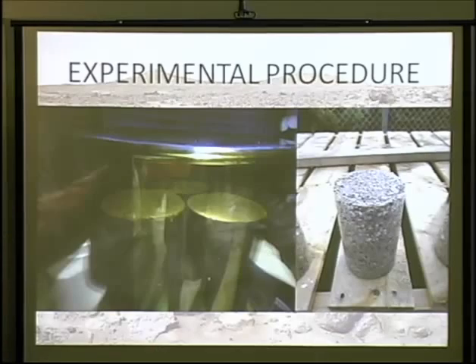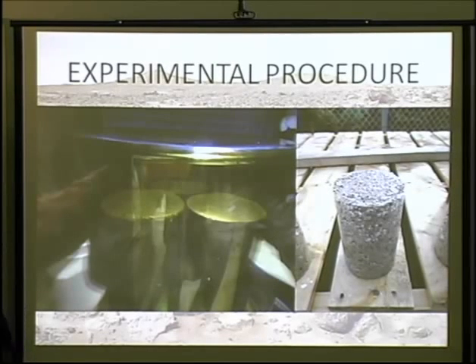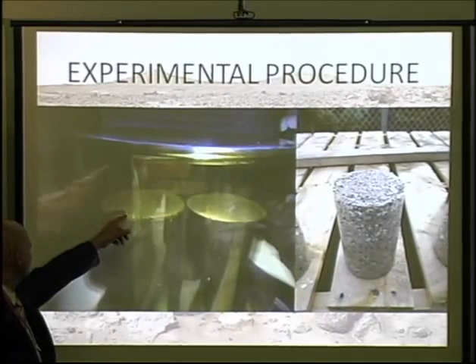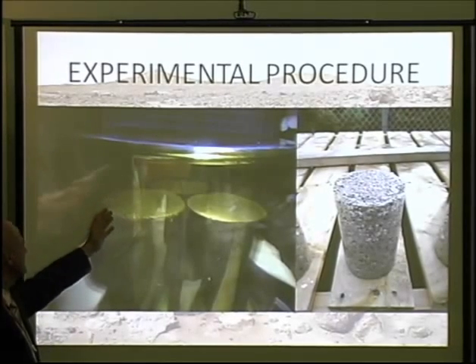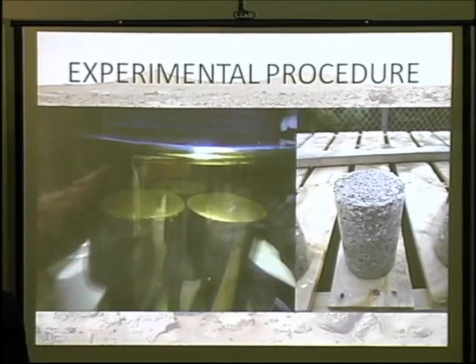So here are my samples in the vacuum chamber at 6 millibars. One problem I had was with dissolved gases that were in the brine and the mixed cement. Since I wasn't able to vibrate the samples to get rid of the air bubbles, I just had to live with the air bubbles. And you can see it bubbling and foaming up, not from boiling, but from dissolved gases.